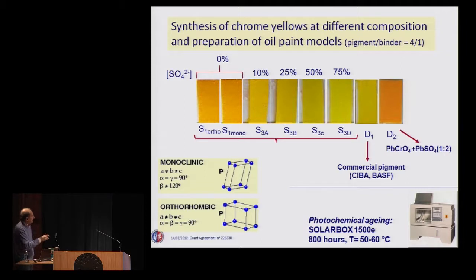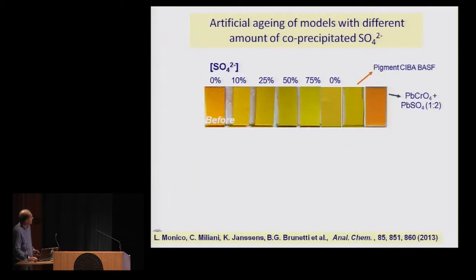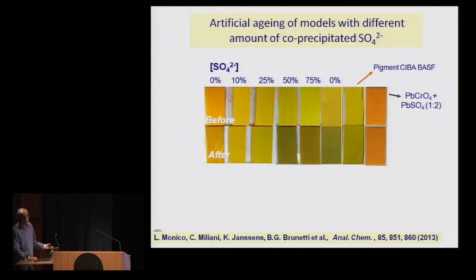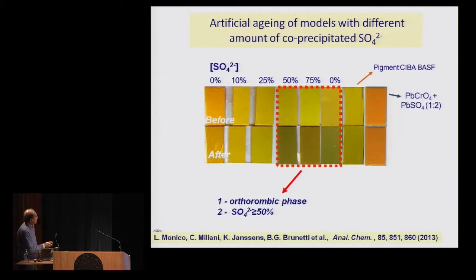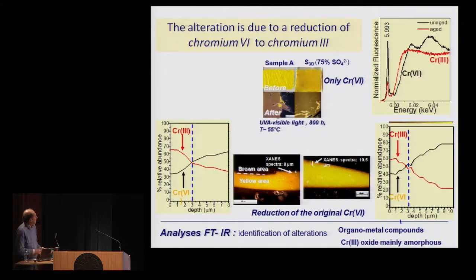and sulfate. And these samples were put in a solar box for 800 hours at 60 degrees centigrade, and what came out from the artificial aging we did was that only some of the pigments that were synthesized were subject to alteration. You can see that these three show a definite darkening. And these three are characterized by the presence of the orthorhombic phase: pure lead chromate in the orthorhombic phase, and two co-precipitated with a high quantity of sulfate, higher than 50%, that again are crystallizing in the orthorhombic phase. All the others are maintained intact or apparently similar.